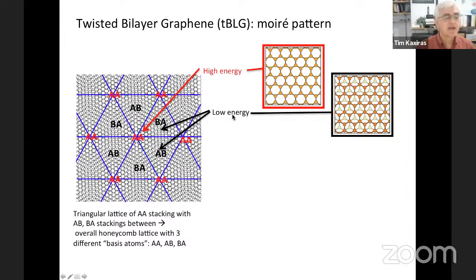And this is the low energy configuration. So the system would like to be in this structure and avoid this structure. This is a high energy configuration as far as atomic structure is concerned. And of course, there are two types of these stacking regions. They're called BA or AB. They're equivalent by a rotation of 60 degrees or 180 degrees. And they're separated by these blue lines, which are domain walls. So that's what you get in terms of atomic structure.